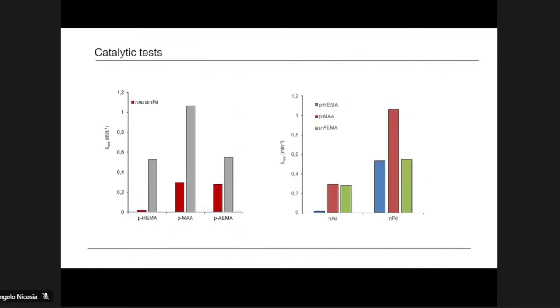Comparing the results obtained, firstly, we have compared two different metals, gold and palladium, and we can observe that the palladium system exhibits the best performance compared to gold, because palladium is a typical system for hydrogenation reactions.